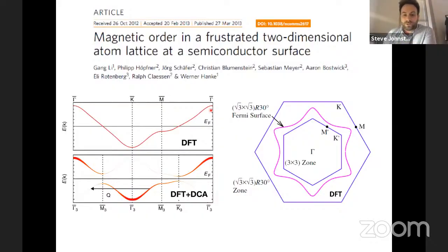And what they found is with DFT calculations, indeed, you get the tin atoms form this nice single band with a bandwidth of about half an eV that passes through the Fermi energy. DFT predicts it's a half-filled band, as you would expect by just counting the orbitals. But what they found is that when they calculated the U and then inserted that into a DFT plus DCA calculation, they found that the U was sufficient to open a gap in the system. And so, this is, again, what you would expect for a Mott insulator, for example.